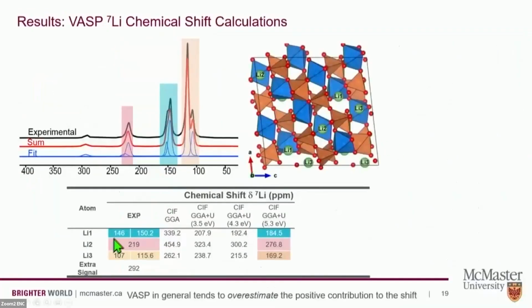And what we see are 3 things. So lithium-1, of course, they don't label in the crystallography the same way that they do in the NMR. So lithium-1 is the middle peak in turquoise. Lithium-2 turns out to be the pink peak at the high frequency, 219 ppm. And we can see that when we just use GGA, these chemical shifts are significantly overestimated, but we add in the U parameter and the chemical shifts come down close to the experimental range. But in general, it's known that VASP overestimates the positive shift contributions. And in this particular occupation of our d orbitals, there's only positive chemical shift contribution, no negative chemical shift. So in the end, they average to be about 50 ppm above our experimental, but showing the same trend.